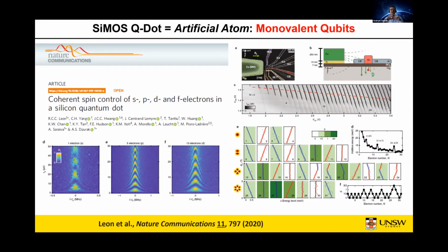It's a two-dimensional circular atom, and Fock-Darwin physics applies. So Fock and Darwin in the 1930s solved Schrodinger's equation for a two-dimensional circular potential, and that's exactly what we have here. And we have a shell structure in our 2D atom, just like one has in a 3D atom. And so the first 4 electrons fill in to so-called 2 valley states, spin down and spin up. So we have 4 electrons in the first valley, and then we jump up to a new orbital level in the 2D atom, and that can accommodate 8 electrons. And then there are 3 orbitals in the next shell which can accommodate 12 electrons. And so our S electrons, we have 4, 8 in P states and 12 in D states.